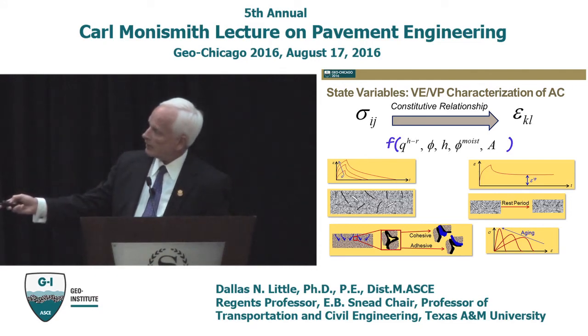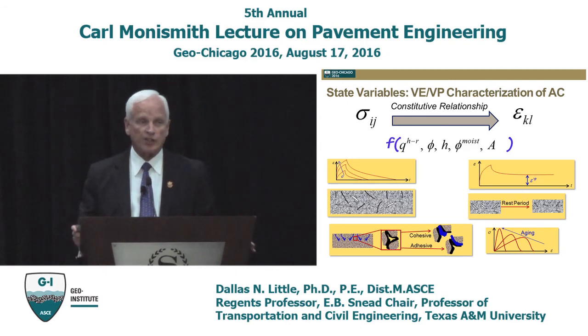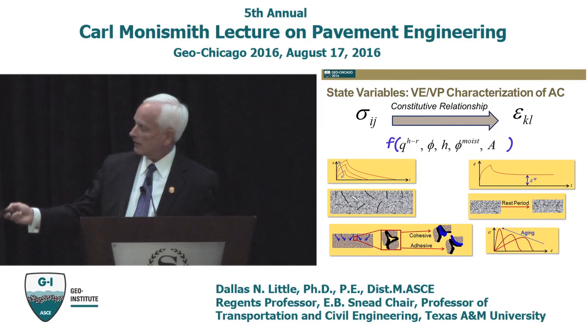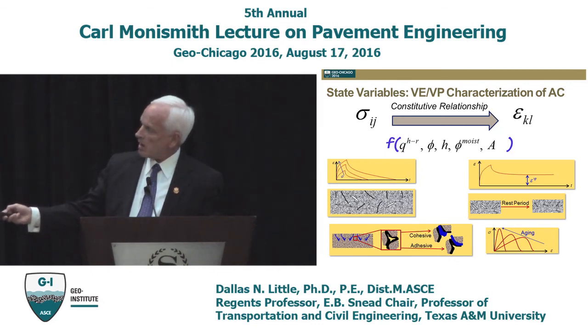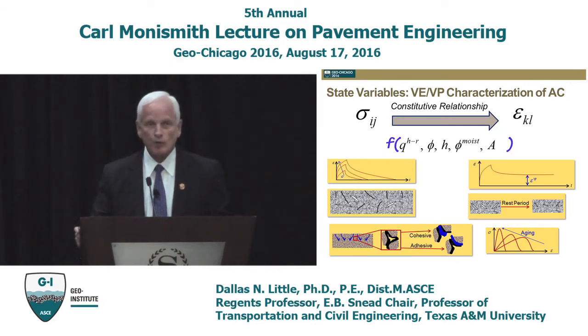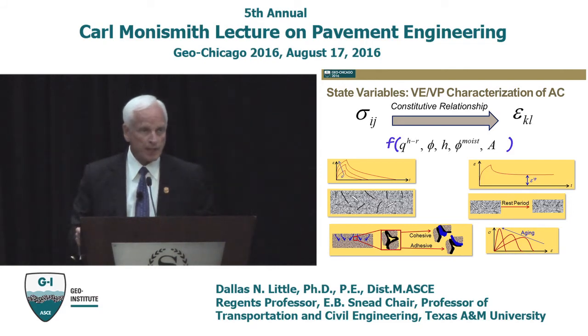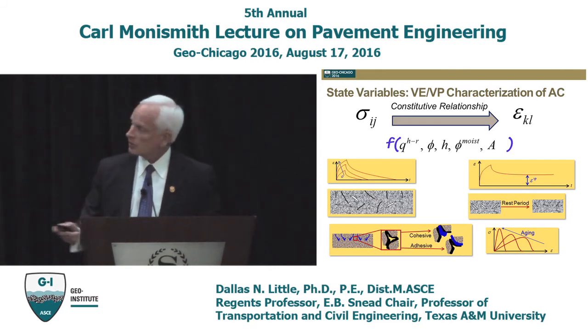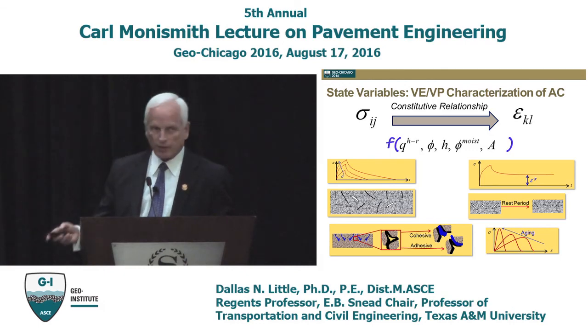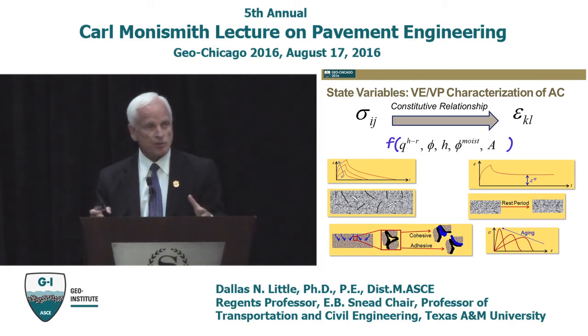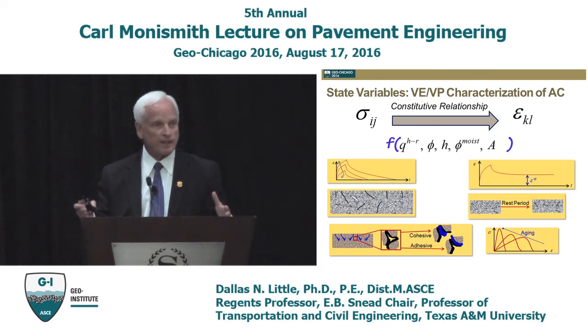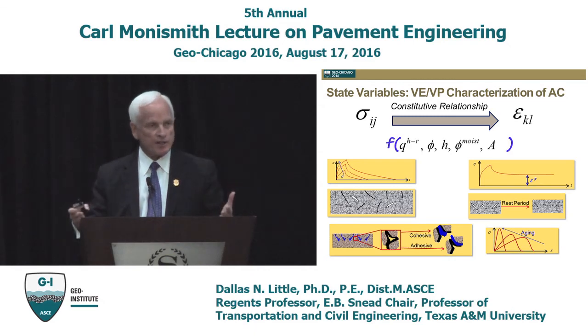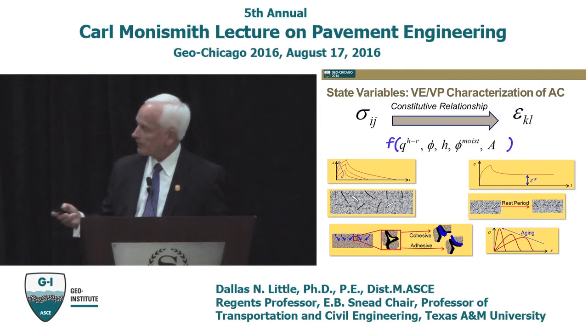The second state variable here is the capital phi term, which is damage. Now, I'm going to talk in just a few minutes more about damage. The way that damage occurs in the model that we're using, which is a continuum damage mechanics-based model, is that we develop a system of what we call microcracks that are due to the excessive stress level. And those microcracks compromise the area that's taking the load in this particular sample.